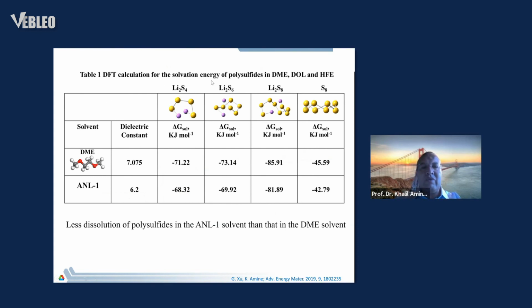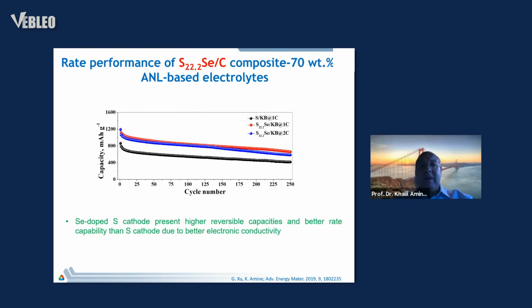My colleague Larry Curtiss did this DFT calculation for the solvation energy. He calculated the solvation in ether base and in HFE. You can see with the ANL-1, which is the HFE, the activation energy is very high, difficult to solvate. So they don't dissolve, basically. And we did a performance test using 70% of the selenium sulfur. In this case, we operate at 1C and 2C. You can see the performance is very good, good cyclability at this very high rate. This is without optimization of the electrode. So there is a tremendous opportunity here.